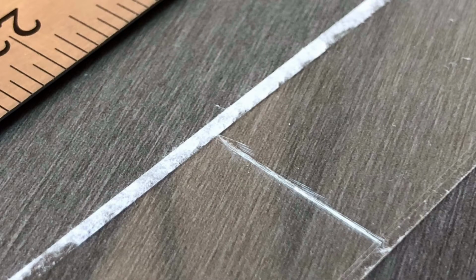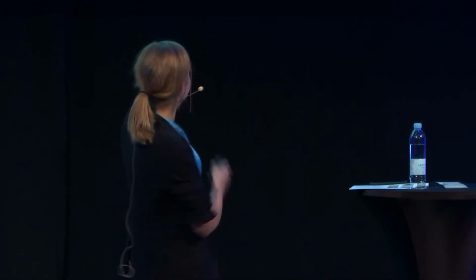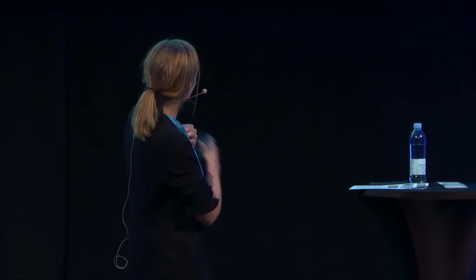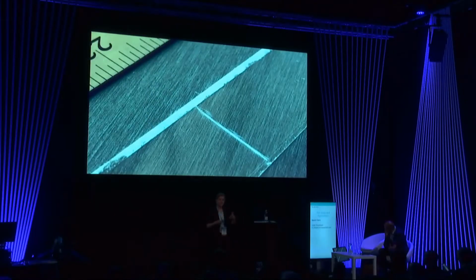So I told you earlier, or I should have told you, that this product has the behavior or breakage pattern of annealed glass. So it breaks in large shards, at least at this aspect ratio, quite large shards. And you can see how much the interlayer retained the glass. So there were very limited pieces of glass that flew off. And what you can see on the right and left side is probably a misalignment of our laminates, but ultimately